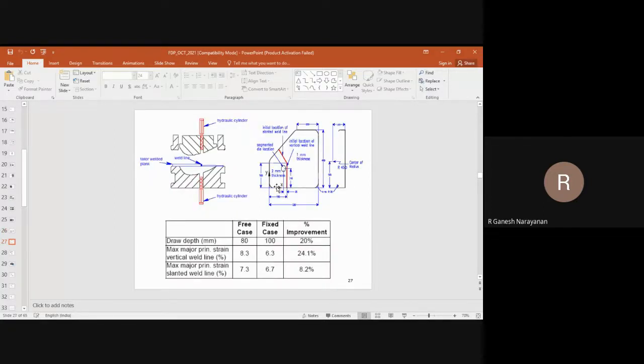Okay, I'm giving an example that in this type of welded blanks, there are chances that you can avoid failure, you can avoid weld line movement by such techniques. Which technique? By providing differential clamping mechanism, differential blank holder. Differential clamping mechanism means this: you apply local pressure such that you resist plastic deformation of these materials, and you avoid such weld line movement and cracking.